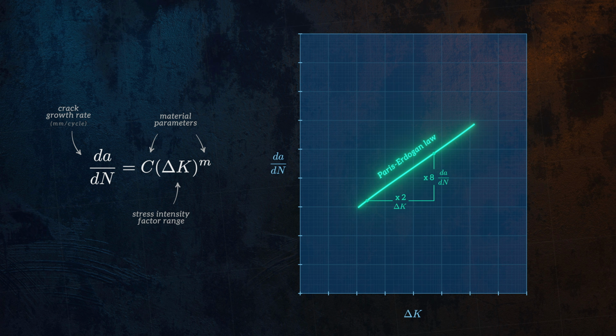For very low delta K values, outside the range of applicability of Paris's law, no meaningful crack growth occurs, regardless of the number of cycles. And for very high delta K ranges, as the peak stress intensity factor approaches the material's fracture toughness, crack growth accelerates massively, beyond what Paris's law predicts, and fracture becomes imminent.